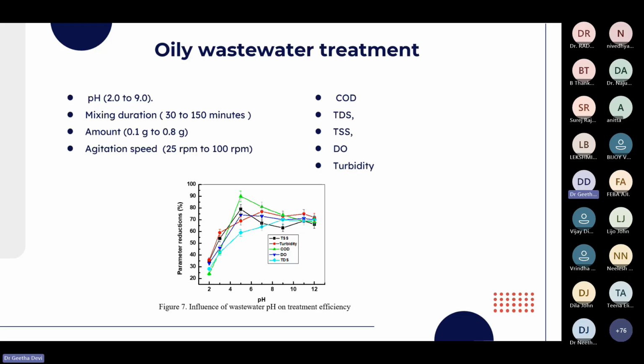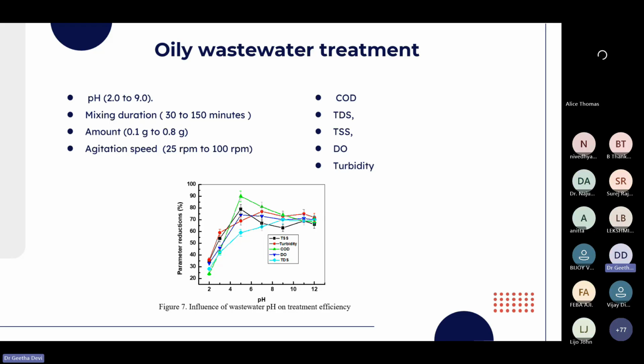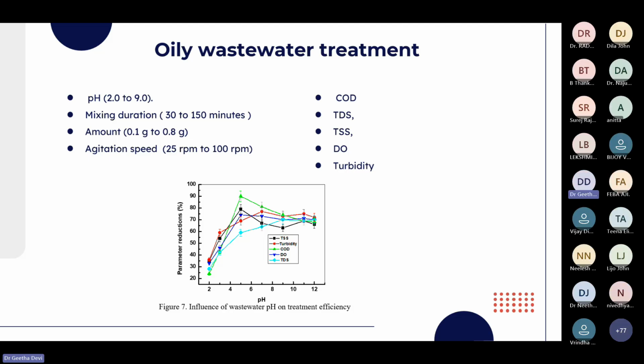And this we have also applied in the removal of COD, TDS, TSS, dissolved oxygen and turbidity present in the oily wastewater, and the pH was varied from 2 to 9. Mixing duration was 30 to 150 minutes, and the amount was varied from 0.1 to 0.8 gram with an agitation speed of 25 rpm to 100 rpm. These are the characterization results.